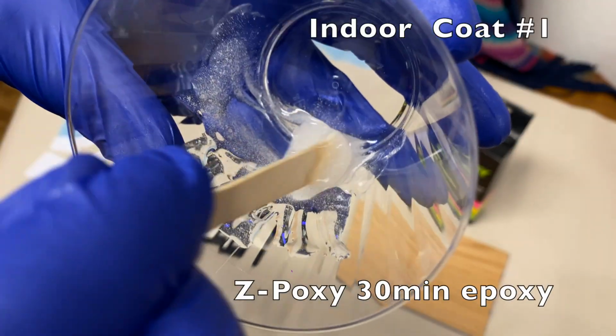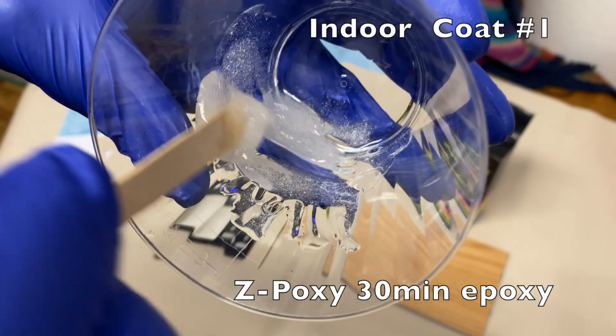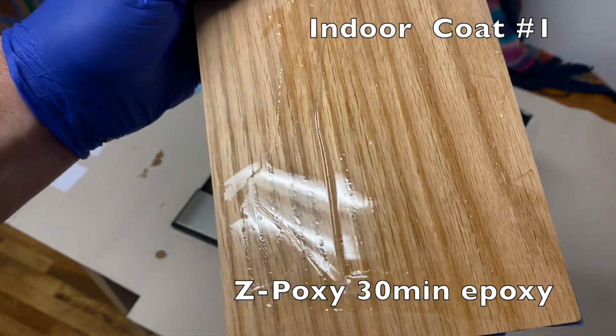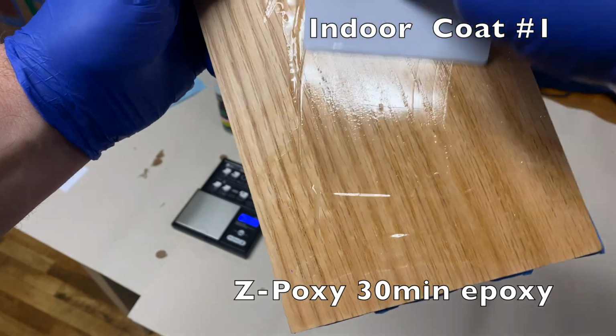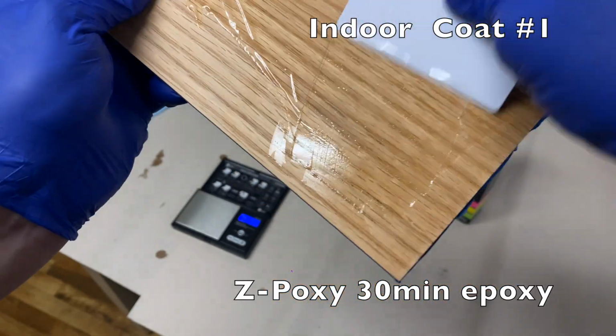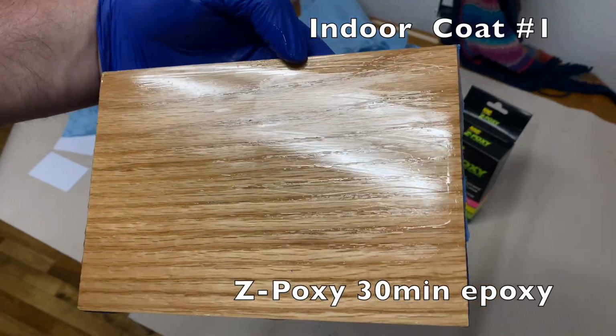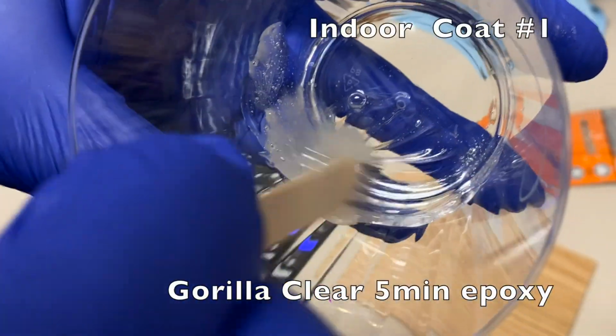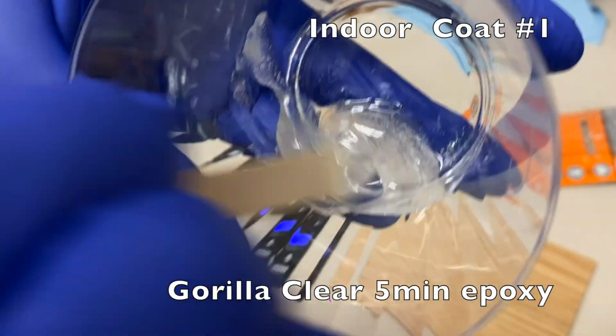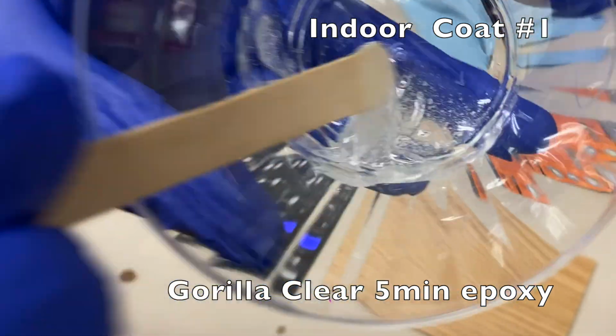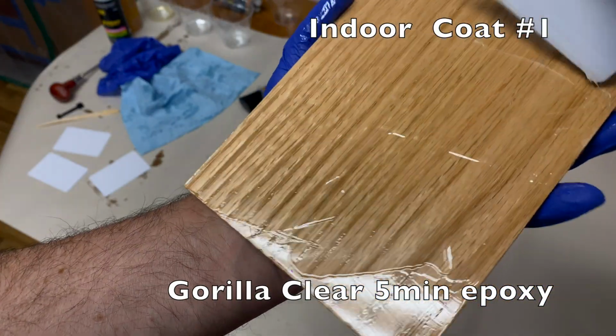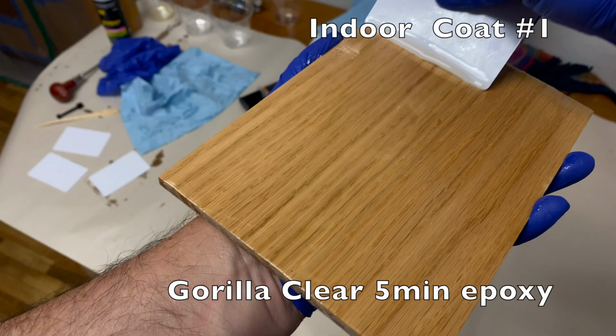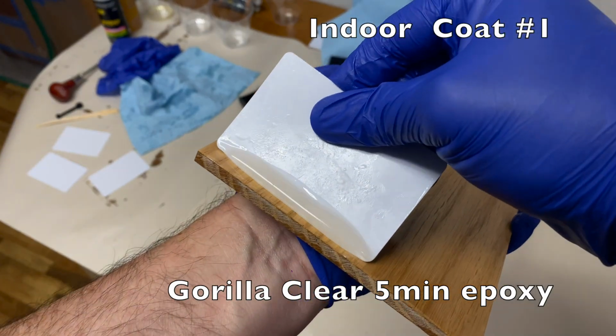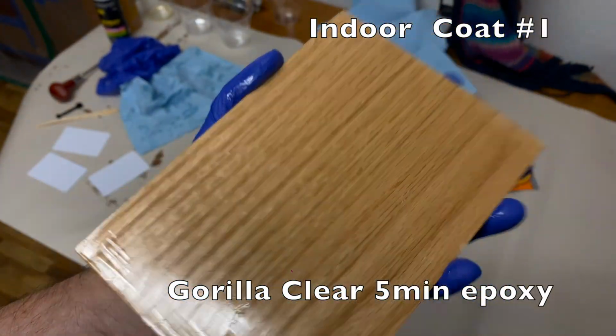The Z-poxy 30-minute epoxy was also easier to apply, and this was actually a nice consistency because it didn't drip or run. I decided to use just one of the 5-minute epoxies since they were so similar, and this Gorilla epoxy went on nicely as well. This is a huge difference from applying it at 50 degrees. It's actually nice to work with, with the exception of having a short set time.